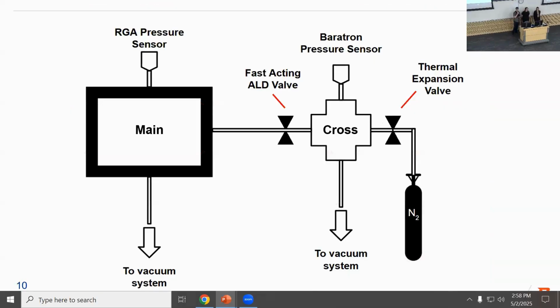So here's another schematic of our system. We've got the cross chamber and the main chamber. Before the cross chamber is filled with nitrogen, it is evacuated, so there's no air contaminating it. It's just pure nitrogen. This is in the millitorr range, so we can use the Baratron pressure sensor, which is an electromechanical system. Because we're not in ultra-high vacuum yet, we can use a much simpler pressure sensor.